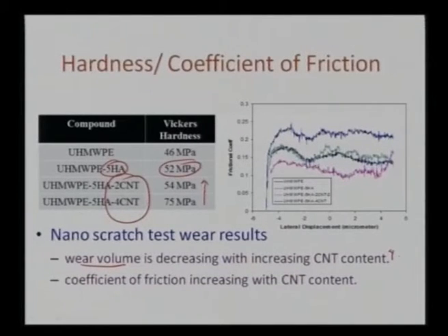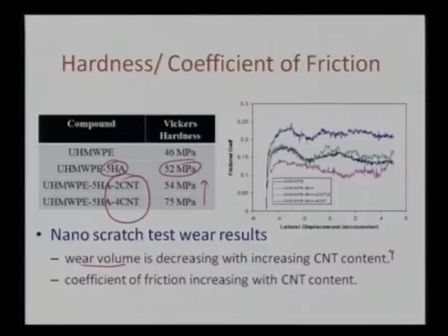So obviously my CNT is improving the wear resistance. Once I am saying that CNT is a lubricant, I should expect that my coefficient of friction should go down. But we are seeing exactly the opposite. In this particular case, we are seeing the coefficient of friction going up with the CNT content. First of all, I had polyethylene; it was showing me some coefficient of friction. Once I am adding hydroxyapatite, I am seeing a decrease in the coefficient of friction.